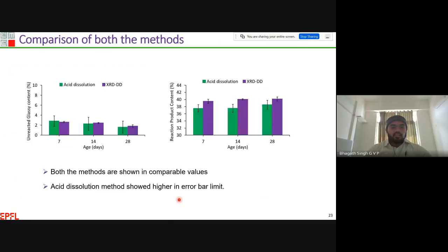Then as usual, I have compared the existing methodology with our XRD direct decomposition method. For both methods, this is the unreacted glassy content and this is the reaction product content at three different ages: 7, 14 and 28 days. At all these ages, both methodologies are fairly matching. Then we can observe the acid dissolution methodology has a higher error bar compared to the XRD direct decomposition method.